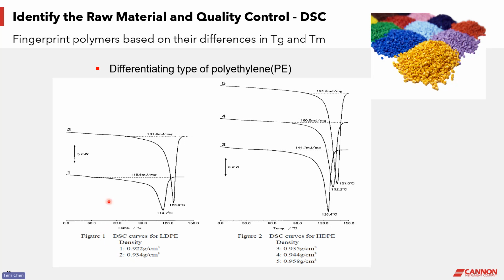The measurement results show that they have their crystals melt at different temperatures. The higher the density, the higher the melting temperature. This same trend can also be observed in the case of HDPE resin. High-density polyethylene resins are mostly linear. Therefore, they usually have higher density with higher crystallinity. Their crystal meltings are also observed at higher temperatures compared to LDPE resins. So figure 2 shows that for HDPE resins, higher density also leads to a higher melting temperature. In polyolefin industries, this DSC measurement is commonly used to identify different grades of polyethylene and polypropylene resins.